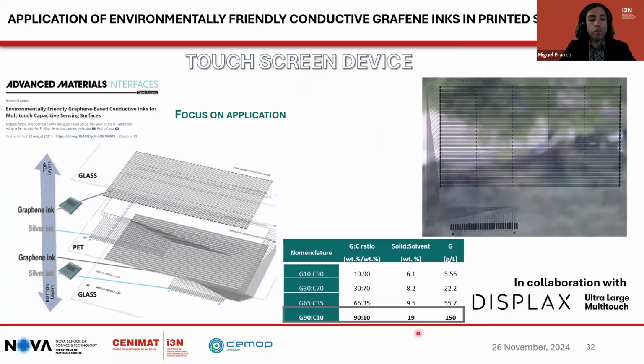Also, the most conductive formulation was employed as a sensing layer of a capacitive touchscreen device. In this case, in cooperation with DISPLAX, a touchscreen company, a screen printed 8-inch capacitive touchscreen device was fabricated. As I said before, graphene was used as the sensing electrodes, and for the interconnections, silver was used. This is the size of an A4 sheet, and as you can see, the spacing between these lines is very low, under 200 micrometers, without having any short circuits. That can show the capabilities of the screen printing technique in its lateral resolution.